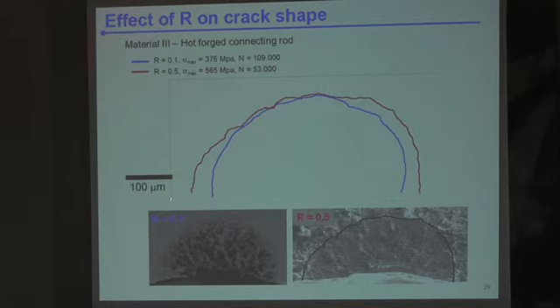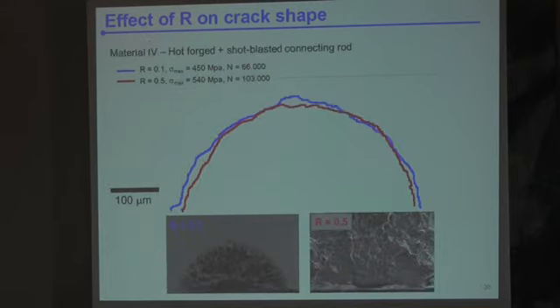That's the same trend. If you cycle at 0.5, you break the sample open, compare that with the synchrotron experiment, then you get a difference where your crack is, if you normalize by this depth here, your crack appears longer at the surface using a higher stress ratio. While if you do that for material number 4, which is the one which had the 0.8 crack aspect ratio, whatever the stress ratio R, you get the same crack front. So in blue, synchrotron experiment, and in red, the lab experiment breaking the sample.